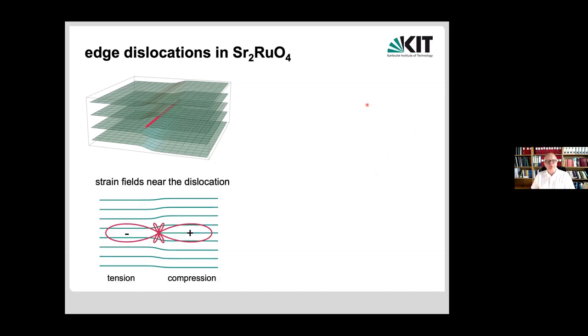So why is that so? Near such a dislocation, what you have is very, very strong local strain fields. So the stress here is about 5 gigapascal near such a dislocation, which is about 5 times what the uniaxial strain measurements usually reach. And you get local tension and compression.